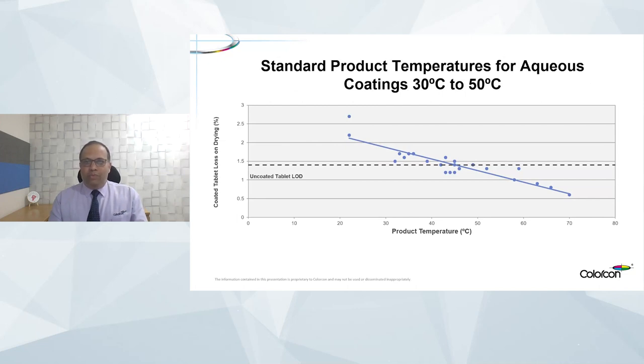Many times it is very important to also be cognizant of the LOD, or the moisture content, of the uncoated core, either at the time of pre-warming or after pre-warming, and then measure it again after the completion of the coating as well as drying. Typically, the temperatures at which standard processes operate are somewhere around 40 degrees Celsius. We do not see a significant difference in the LOD of the tablet, but it is important to be aware of this to make sure that the process efficiency and the overall weight gains are in line with our expectations. That is a good practice when we are designing or optimizing a process. But at these temperatures, we should not see more than 0.5% or a maximum of 1% difference from the tablet which was starting to coat.